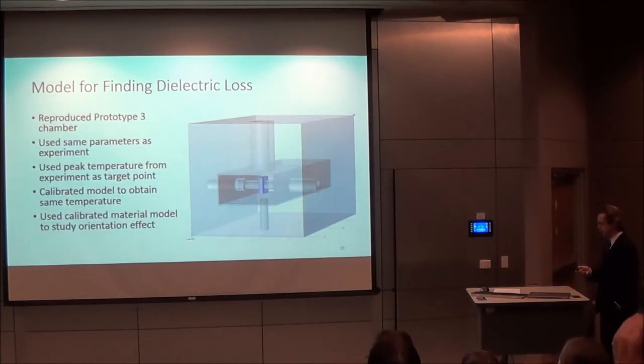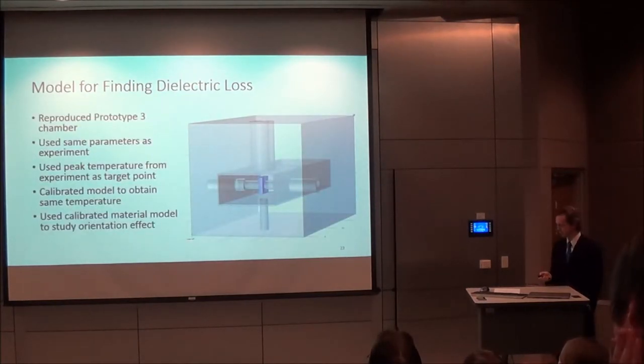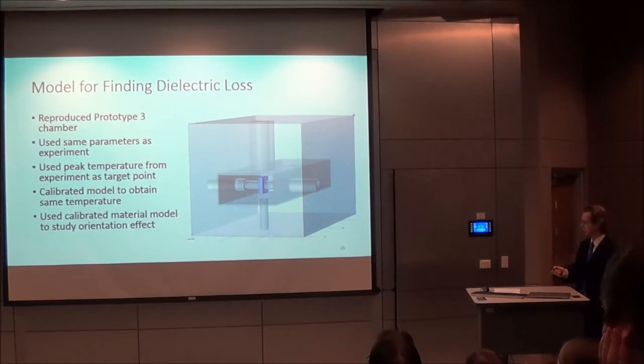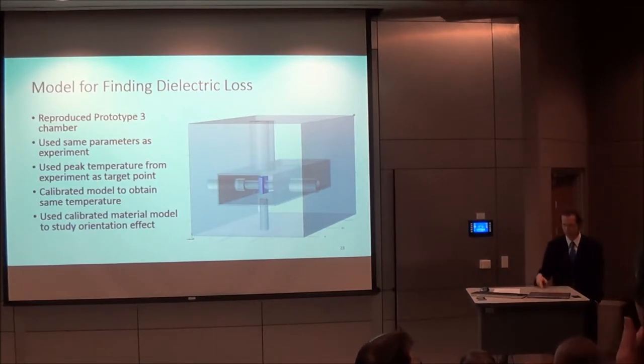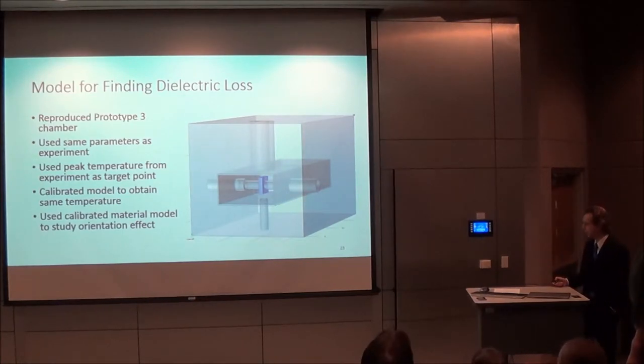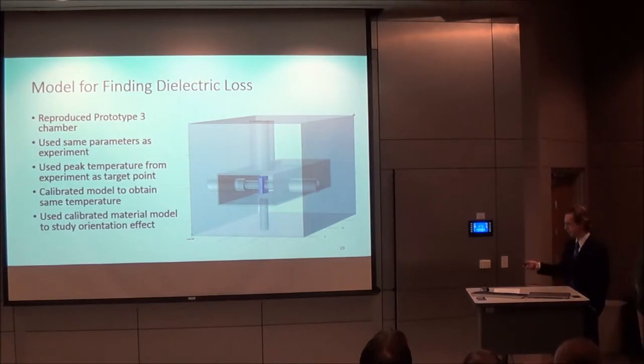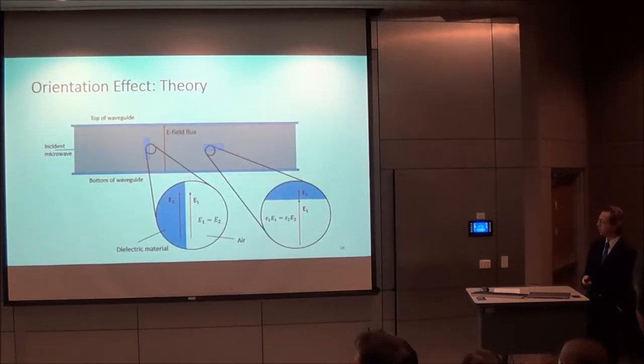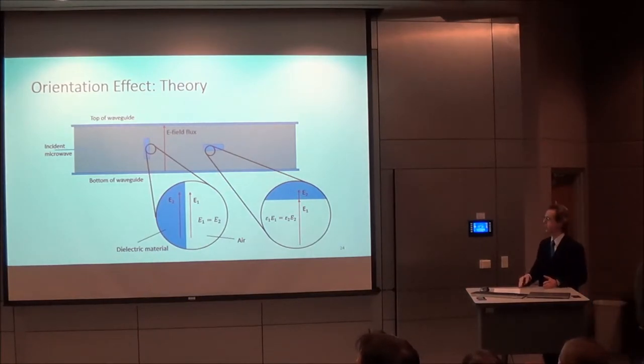And so this is the numerical model, the geometry of the model used to find the dielectric loss factor of cordierite. This is the cordierite brick. It's a piece that's used in a backing bar to put an underbead on a weld, but it was just an arbitrary ceramic that was readily available. And so basically the same parameters are used in the experiment, the final temperature is found, and that's used to calibrate the other numerical models. So this data was used in the numerical model to evaluate the orientation effect.